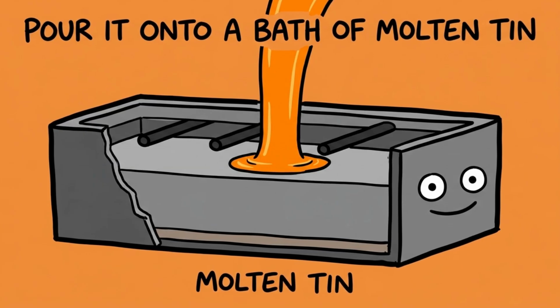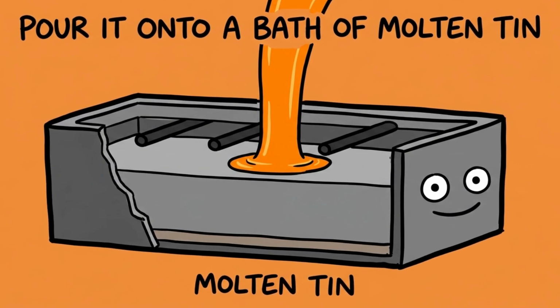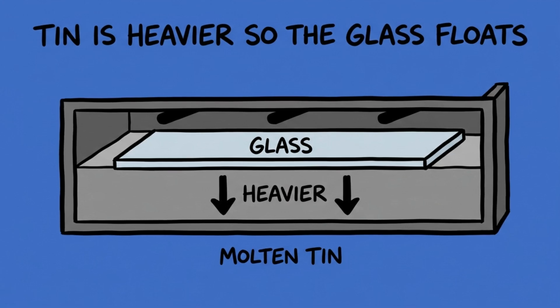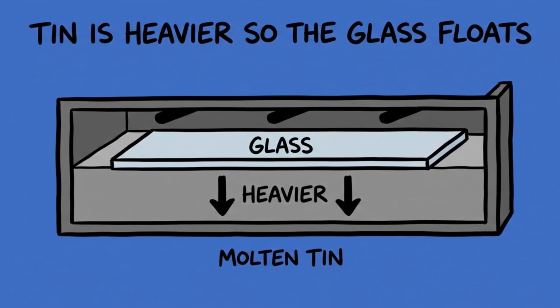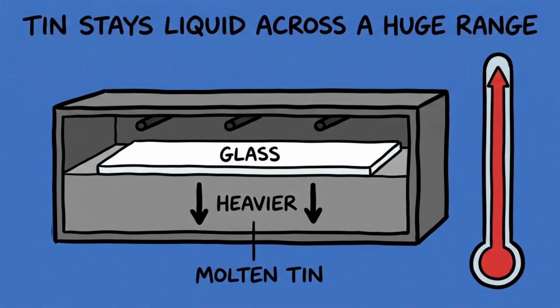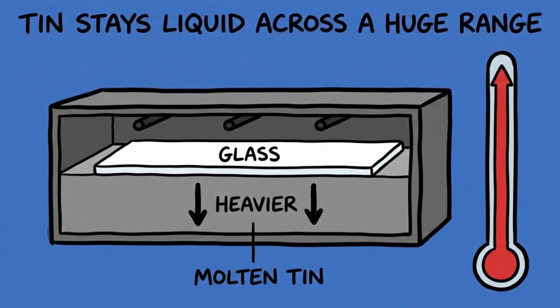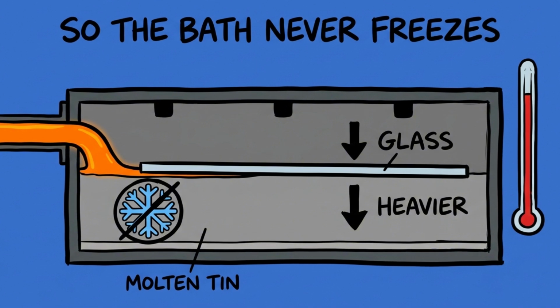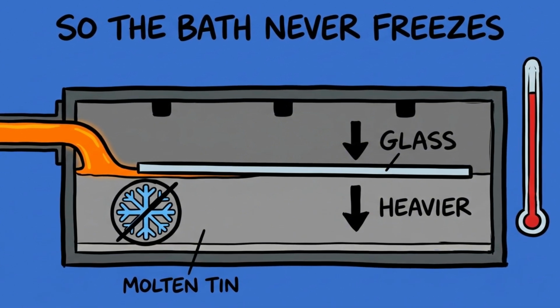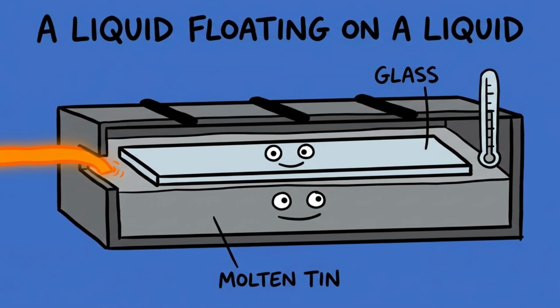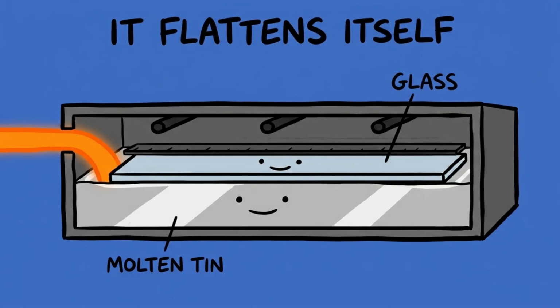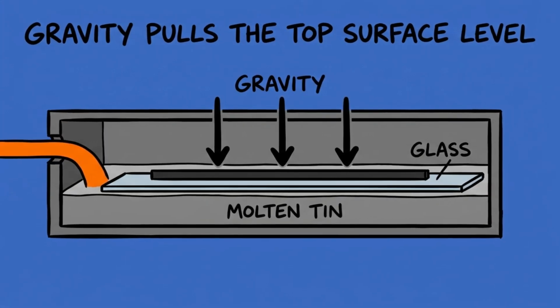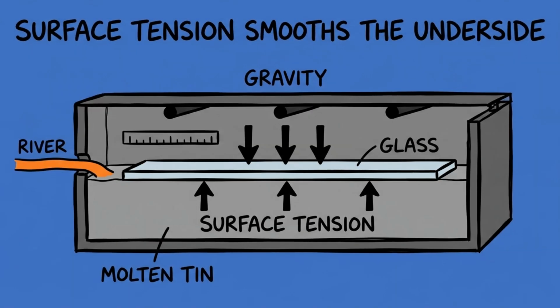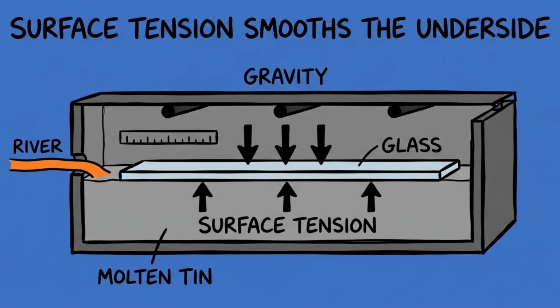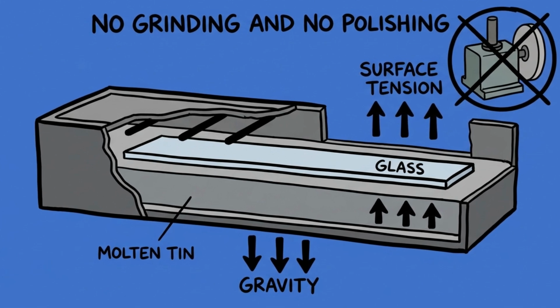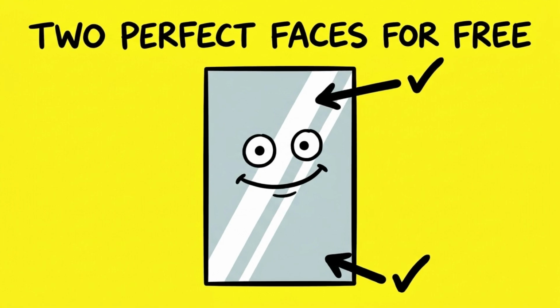Pour the molten glass onto a bath of molten tin. Watch what that does. Tin is denser than glass, so the glass floats on top. Tin also stays liquid across an enormous temperature range, so the bath does not freeze under a river of hot glass. And a liquid floating on a liquid does something no machine can match. It flattens itself. Gravity pulls the top surface level. Surface tension smooths the underside against the tin. No grinding, no polishing. 2 perfect faces for free.